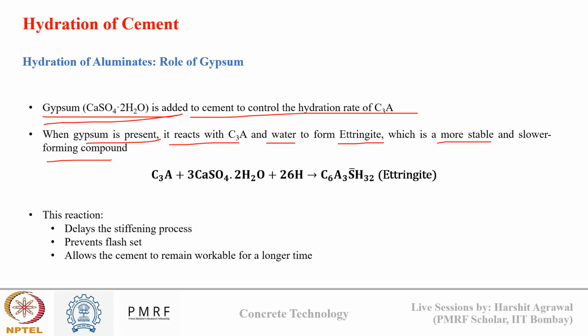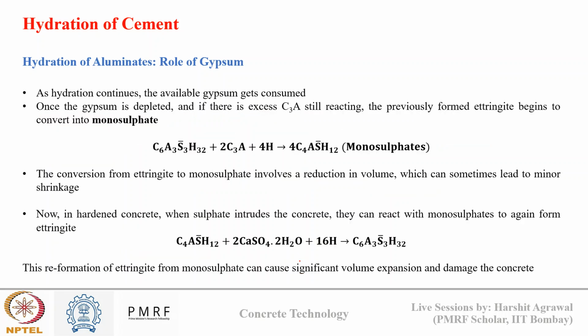So what will happen if there is no gypsum? C3A reacts with water to form calcium aluminate hydrate. But if there is gypsum present, C3A will react with gypsum in the presence of water to form ettringite, and this is a slow forming compound. It won't form instantaneously, it will take time to form. If it takes time to form, it will consume water slowly. If water is consumed slowly, there is more water available to give concrete the flowability that we need. So gypsum delays the stiffening process, prevents flash setting, and allows the cement to remain workable for a longer period of time.